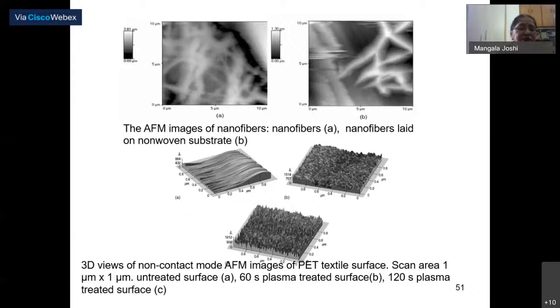carboxyl or hydroxyl groups will also be present, that also can be seen, but at least the roughness has gone high. And in the 120-second plasma treated sample, you can measure the roughness also. There is a roughness parameter which you can measure on AFM, and this can give an idea about how much change in the sample topography there is. Next slide.